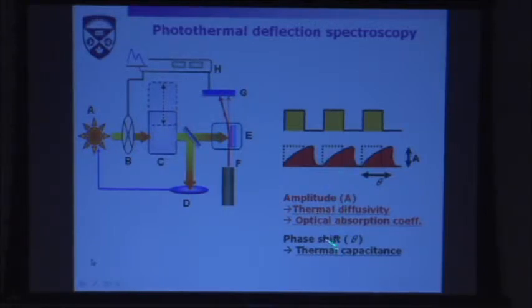If I have the thermal diffusivity and the thermal capacitance, I know the thermal conductivity. If the optical absorption coefficient, so the amount of light that is absorbed by the sample and dissipated into heat, is known, but this can be known if I know the optical properties of my sample that I can measure by UV visible measurements or things like this. So here we go. We compared, of course, for a while this technique with other techniques to make sure it works. It's simpler than them. You can also estimate if there is a thermal sink on the substrate, making a measurement on the other side to calibrate it. There are ways.